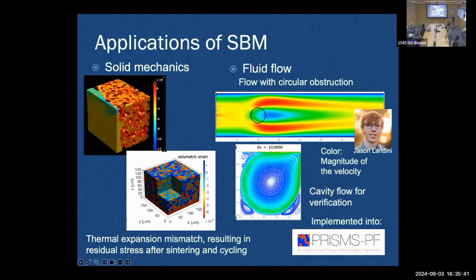So those are both thermal expansion mismatch stress, residual stress from the thermal expansion coefficient mismatch. Because these materials are made at high temperature, then at room temperature there is a differential volume change, and you end up with some residual stress. I'm going to write more about this, but this is the fuel cell material. This is battery material.